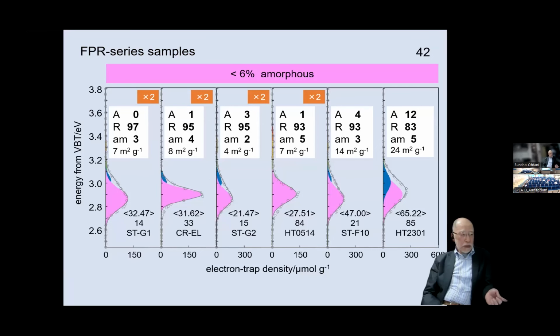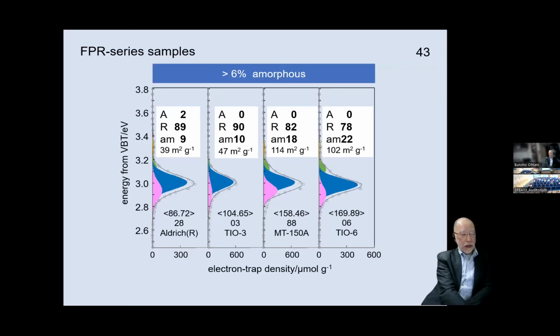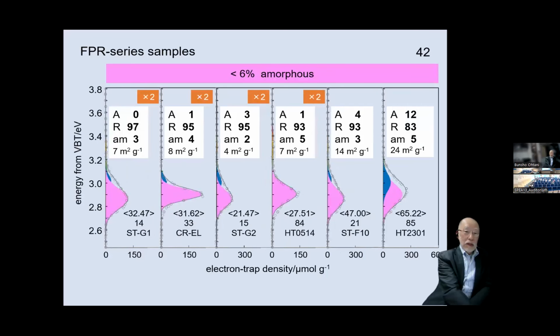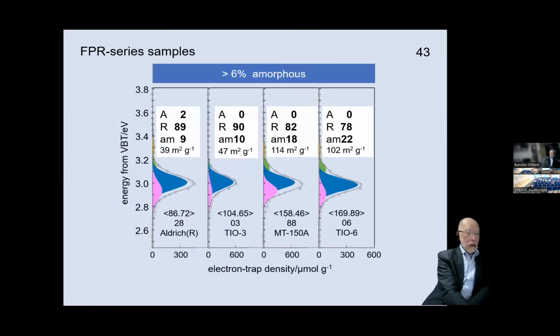And if the amorphous content is lower than 6%, the surface is almost rutile with amorphous, but almost all the surface is exposed as rutile surface. However, if the amorphous content is higher than 6%, in those samples the specific surface area is a bit higher than the smaller particles. And in this case, the small rutile particles are almost covered with amorphous. So this is completely different from those large rutile particles. So it is necessary to notice this point if we discuss the activity of rutile samples.